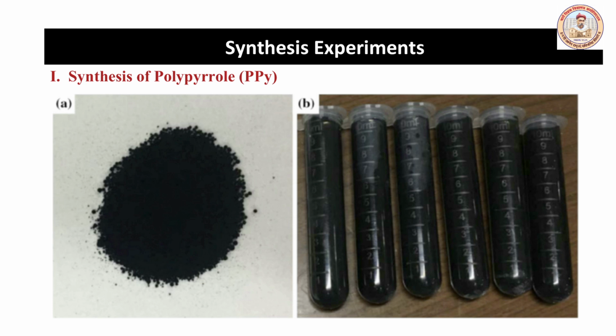The product was filtered under reduced pressure, washed with distilled water until the filtrate became colorless and dried under vacuum at room temperature. Polypyrrole powders with different molar ratios ranging from 0.5 to 3 were prepared. The picture shows the different polypyrrole powders prepared at different molar ratios. Batch 2 of synthesis experiments is of polypyrrole polyvinyl alcohol composite films.